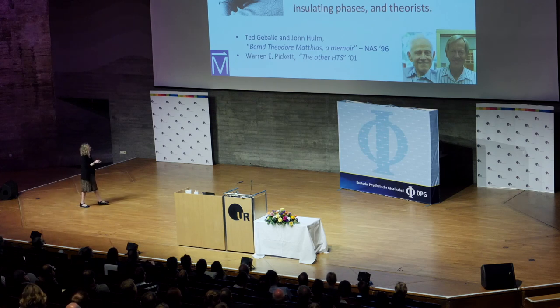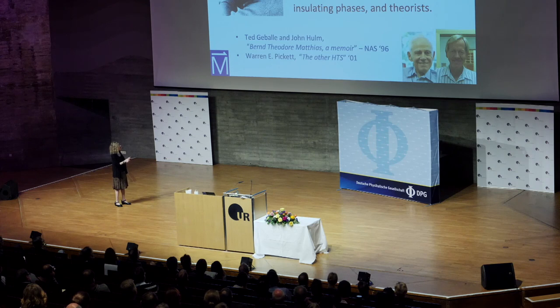He had a rule there. Some of his rules were very good: stay away from oxygen, magnetism, insulating phases, and theorists. So what we do know is that the highest temperature superconductors are next to a magnetic quantum critical point. We need magnetism. And they also have oxygen in them, and their ground state is insulating. That's the cuprates. So Bernd Matthias was right, 100% right, for conventional superconductors. But for unconventional, everything's just really wide open right now.